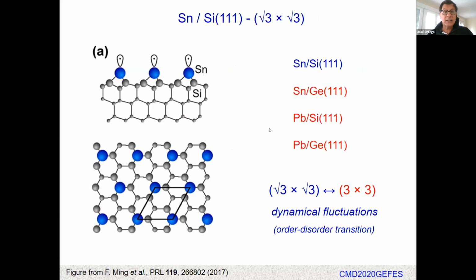So this is the host lattice. The host surface is a well-known surface with tin on silicon. This is 1/3 of a monolayer with a √3×√3 surface. This is a well-known surface where we have tin atoms on T4 positions on the silicon surface, and they have this geometry. This belongs to a family, to a group of surfaces which are similar, with tin or lead atoms on top of silicon or germanium-111. And one of the particular things that these systems display is a transition from the room temperature symmetry, √3×√3, to a 3×3 symmetry at lower temperatures for these three systems, but not for the system we are now using in this work.